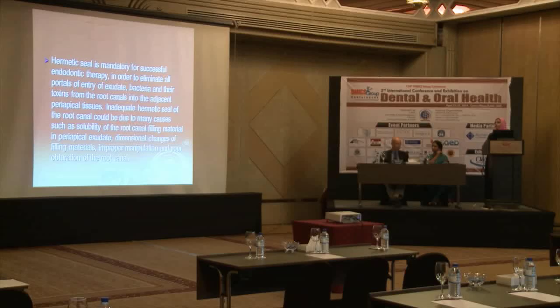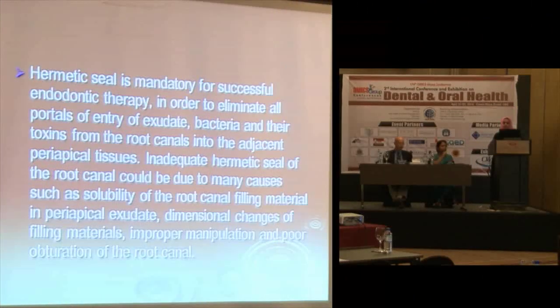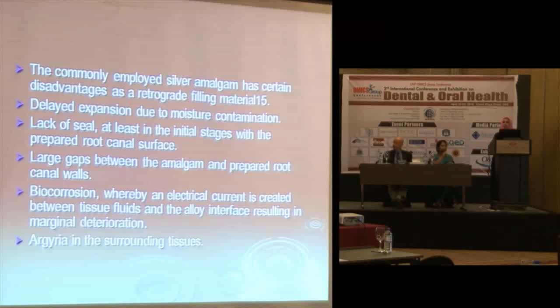A hermetic seal is mandatory for successful endodontic therapy in order to eliminate all portals of entry of exudate, bacteria and toxins from the root canals into the adjacent periapical tissues. Inadequate hermetic seal of the root canal could be due to many causes such as solubility of the root canal filling material in the periapical exudate, dimensional change, improper manipulation and poor obturation. The commonly employed silver amalgam had certain disadvantages as a retrograde filling material: delayed expansion due to moisture contamination, lack of seal, at least in the initial stages, with the prepared root canal surface, large gaps between the amalgam and the prepared root canal walls, biocorrosion and argyria in the surrounding tissues.